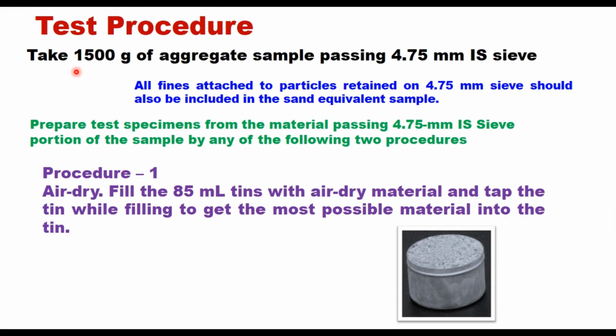The first step is to take 1500 gram of aggregate sample passing 4.75 mm IS sieve and break down any lumps of material in the coarser fraction to pass the 4.75 mm sieve, and all fines attached to particles retained on 4.75 mm sieve should also be included in the sand equivalent sample. The sample for testing can be prepared by any of the two procedures. The procedure one is air dry.